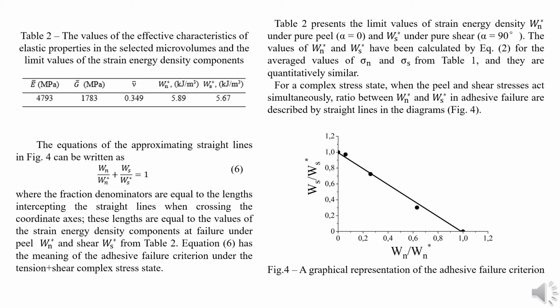For a complex stress state, when the peel and shear stresses act simultaneously, the ratio between Wn and Ws and adhesive failure are described by straight lines in the diagram in figure 4. The equations of the approximating straight lines in figure 4 can be written as Formula 6, where the fraction denominators are equal to the lengths intercepted by the straight lines when crossing the coordinate axes. These lengths are equal to the values of the strain energy density components at failure under peel Wn asterisk and shear Ws asterisk from Table 2. Equation 6 has the meaning of the adhesive failure criterion under the tension plus shear complex stress state. Note that the linear failure criterion similar to 6 is used to predict crack propagation conditions, but with energy release rate Ge used instead of strain energy density.